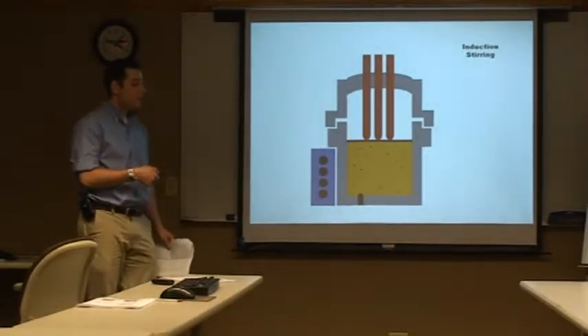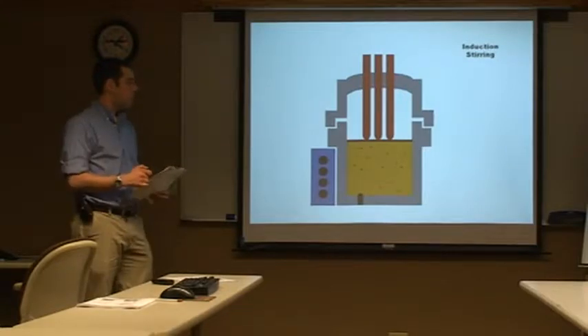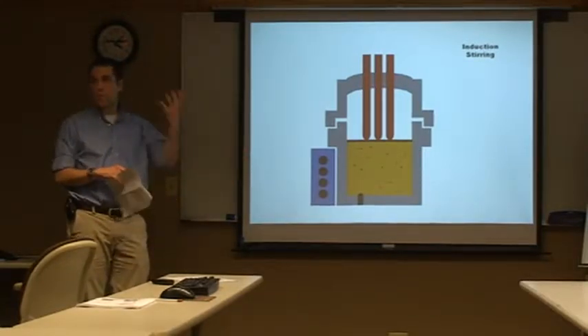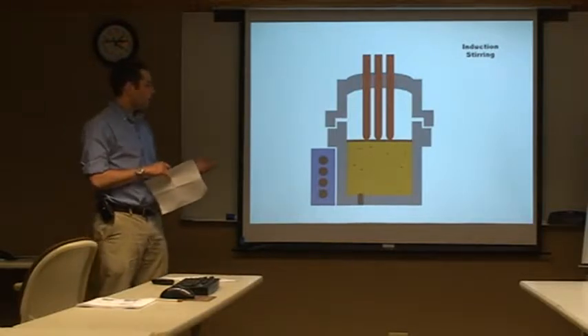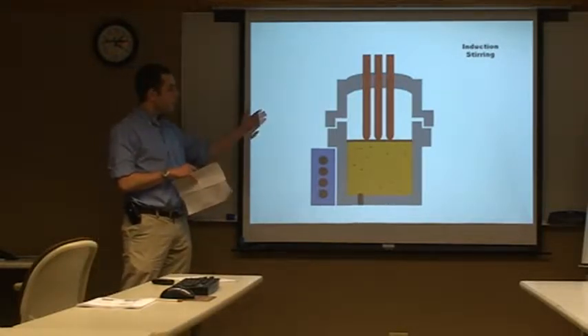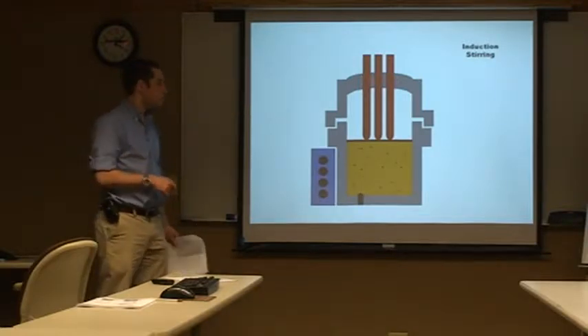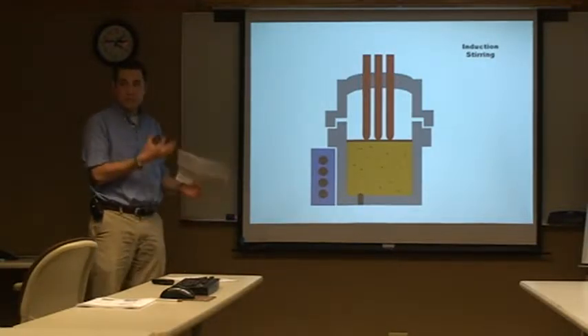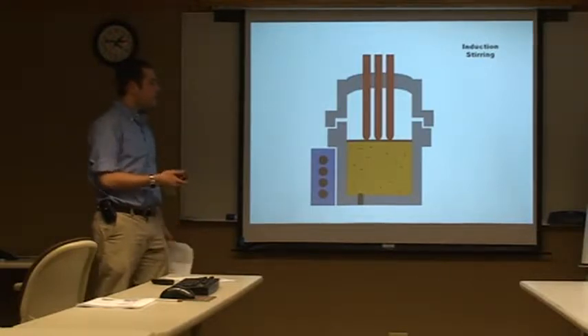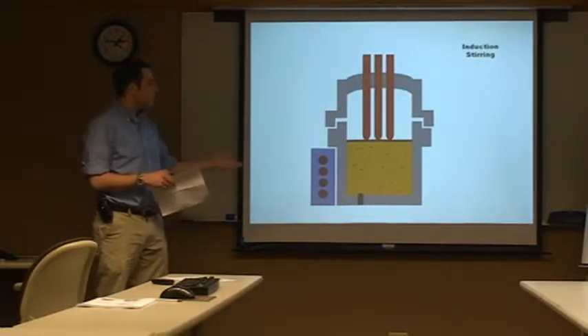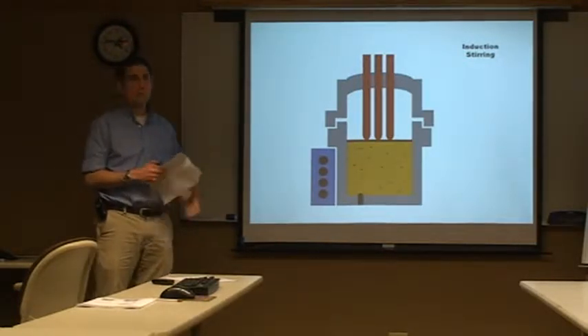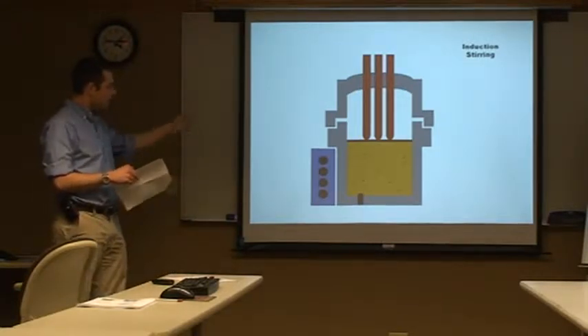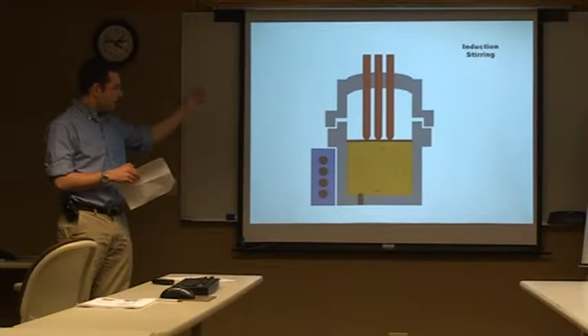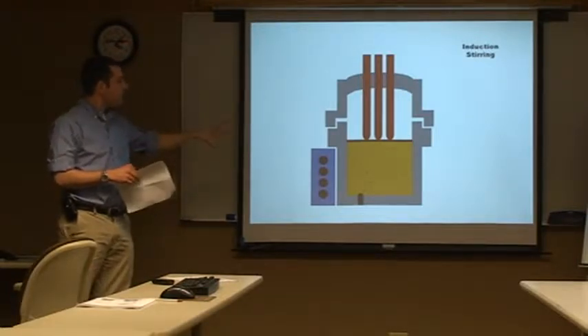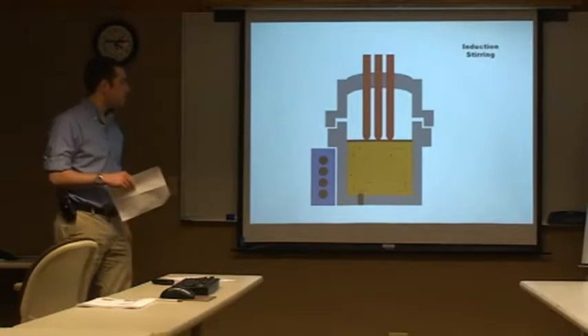One of the benefits of this process is there's going to be some non-metallics in the steel from when we melted down the scrap, and not all of them will be able to float up into the slag because not all of them have enough buoyancy to get up there. But when we're mixing the steel with induction stirring, we allow opportunities for those non-metallics to get up into the slag and clean our steel that way. And you can see that here. They're exaggerated in size, of course, but as we mix them around, we get them to interact with that slag layer and clean out our steel a little bit.